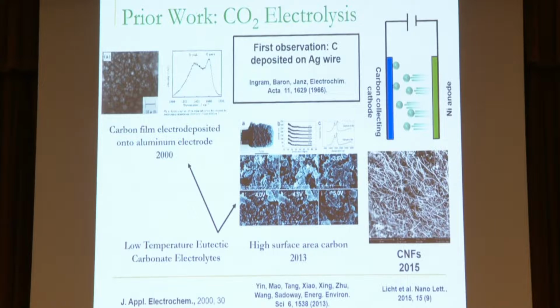Okay, so we're not the first to do this. Actually, carbon deposition on a silver wire was done back in 1966. Just like batteries, it's not a new field, but people haven't been able to synthesize valuable materials. They've made a lot of carbon junk over the years. And so when we started this, the most promising one was this work where they made these fibers, which are actually micron sized. They call them nano. But of course, you'll notice that to be nano, you have to have one dimension less than 100 nanometers in principle, but they weren't nano.